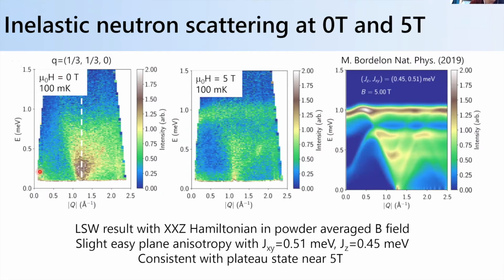So this is powder averaged inelastic scattering. Again, this is energy transfer as a function of momentum transfer. And so what we're doing is we're exciting, if it was an ordered system, spin wave excitations. But instead, what we see is, about this third-zero wave vector, which is the two-dimensional wave vector for 120-degree order, we see this sort of mush of spectral weight.